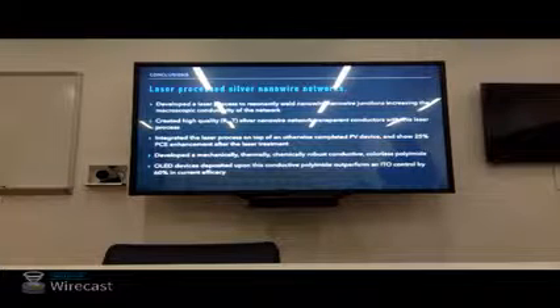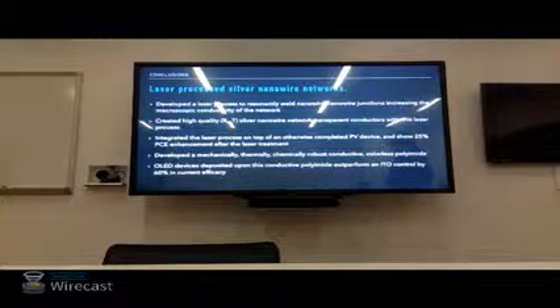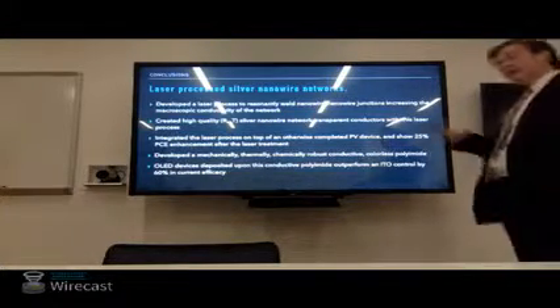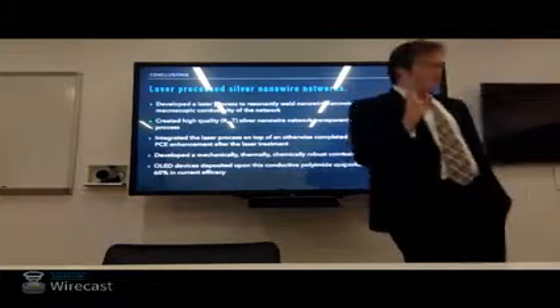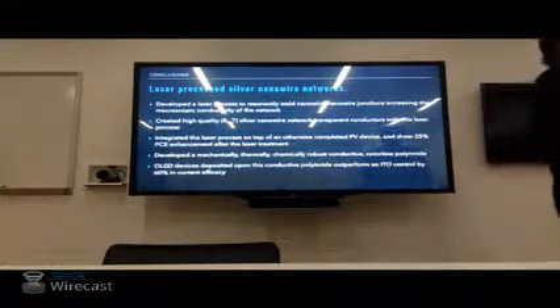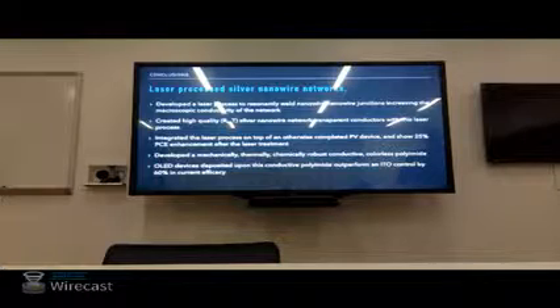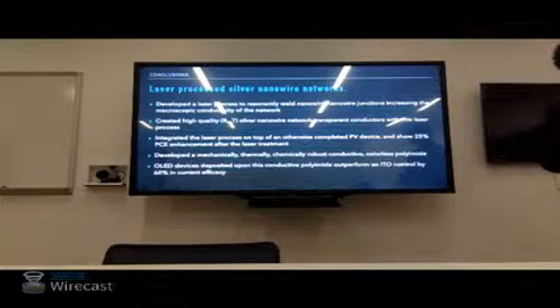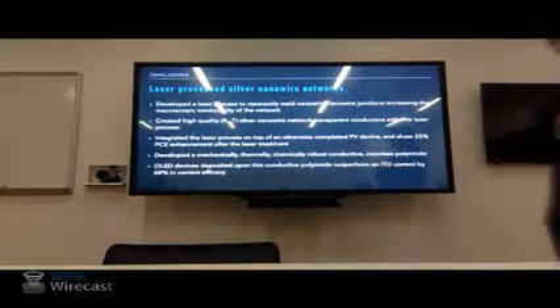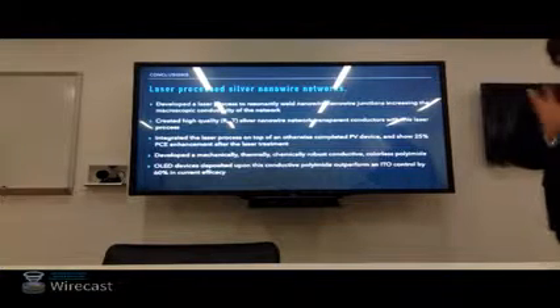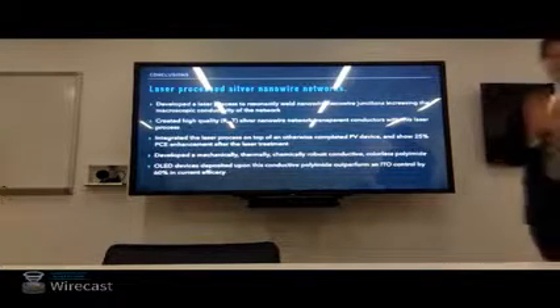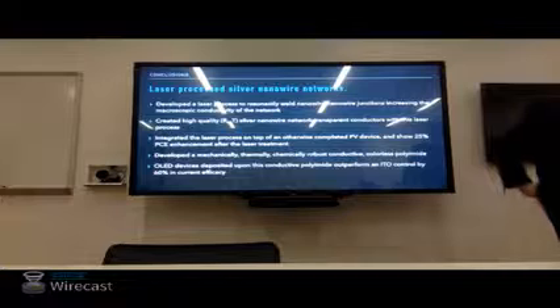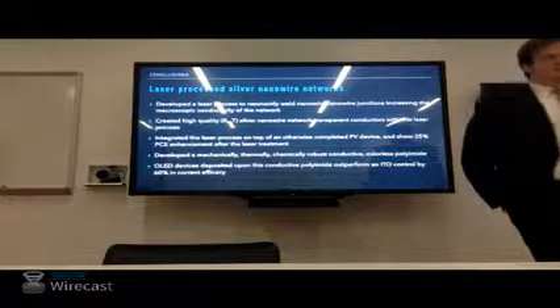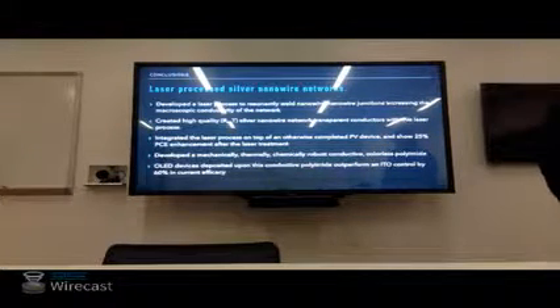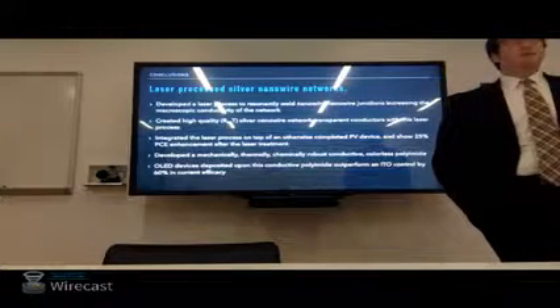Oh, I'm sorry. So those numbers there, those were on glass substrates? So the ITO, actually, I'm misspeaking. Let me back up. The ITO is on glass, correct. And the glass is a lower index of refraction than the polyimide. The polyimide is freestanding, flexible when we measure it. So there's no glass there. Your data was all on the plastic substrate with the high index? That's correct. No glass when we measure.